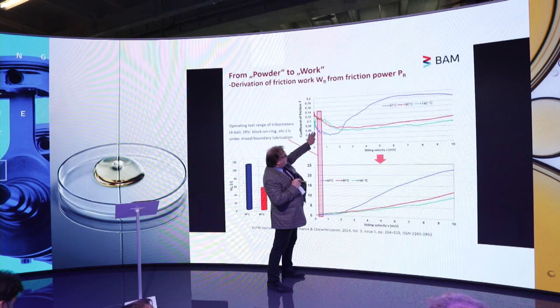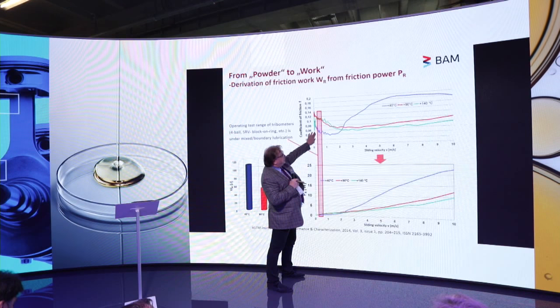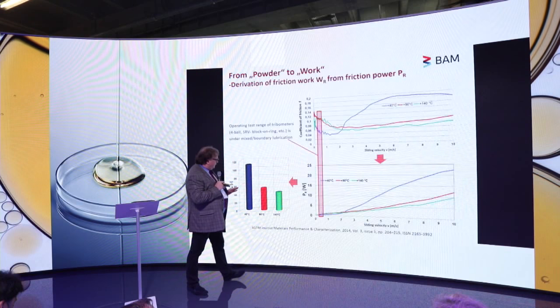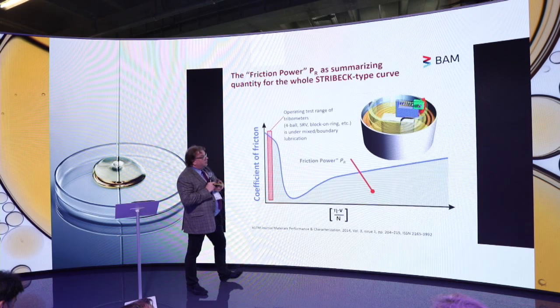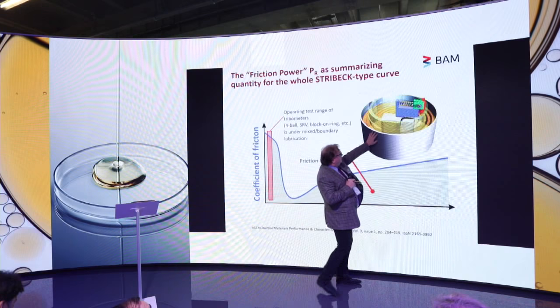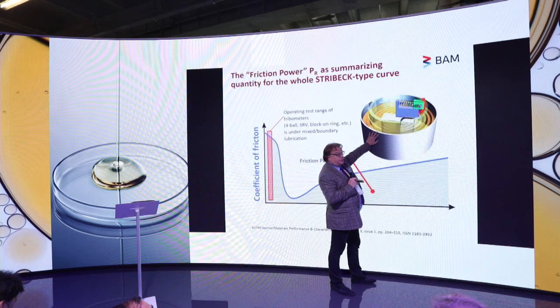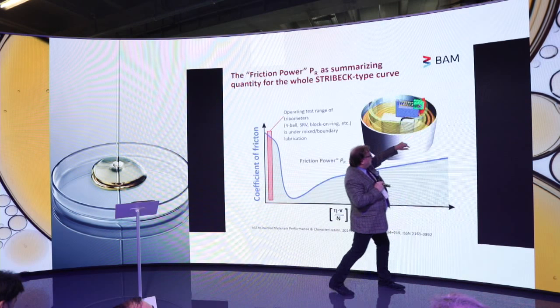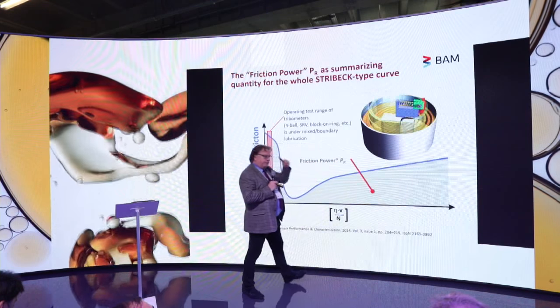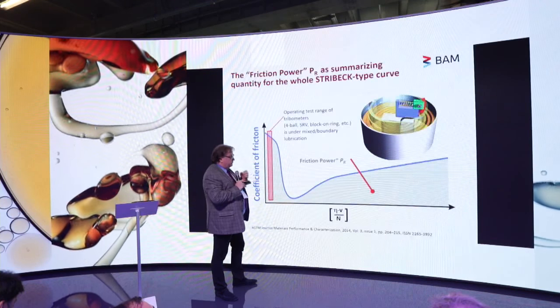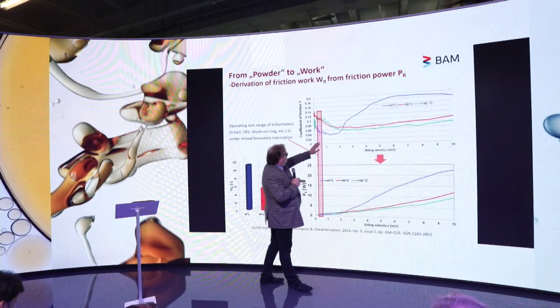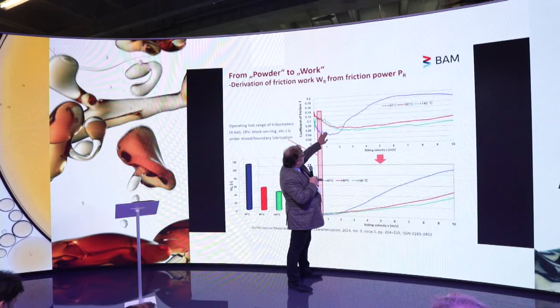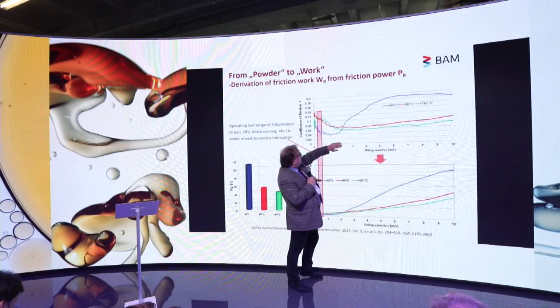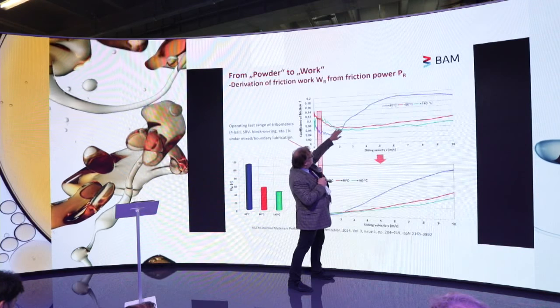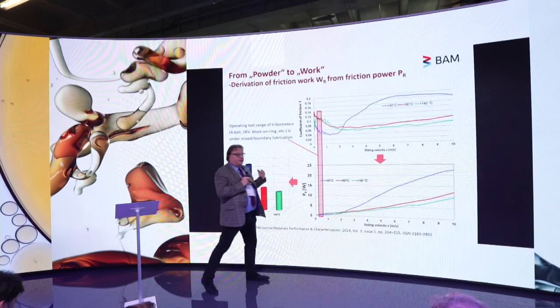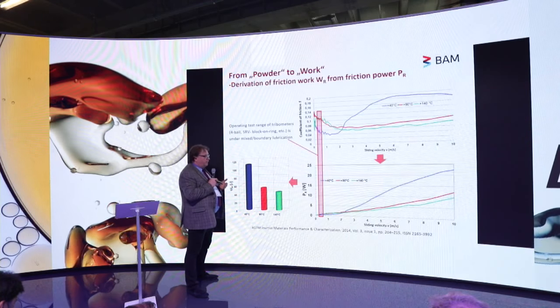Here you see real Stribeck curves of piston ring and cylinder liners. You need a liner cut out from an engine. You have a piston ring and you spin. You see that at room temperature the hydrodynamic friction is really high, and when you increase your oil temperature, friction goes down. That's why under city driving and cold start you have high friction.